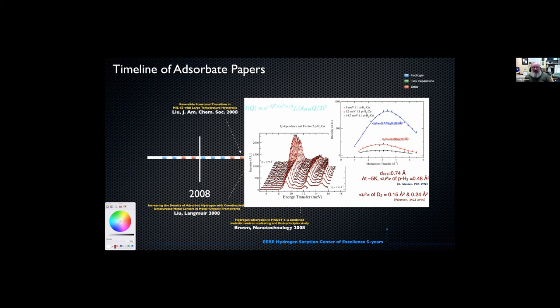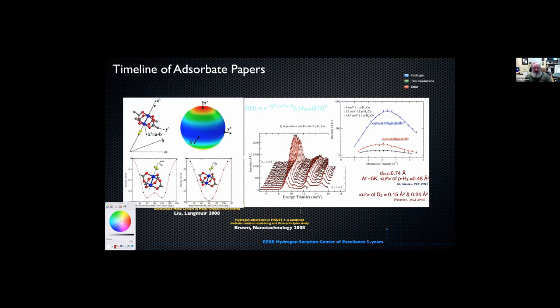The other thing is that we don't have to invoke a hydrogen-hydrogen elongation to understand the Q dependence of those peaks. Taner Yildirim did some nice work looking at the total potential of a hydrogen molecule that's attached to this cluster in three-dimensional space. The volume there is on the top right. And if you solve that for the rotational Schrodinger equation, it gives you the transitions that you'd expect.